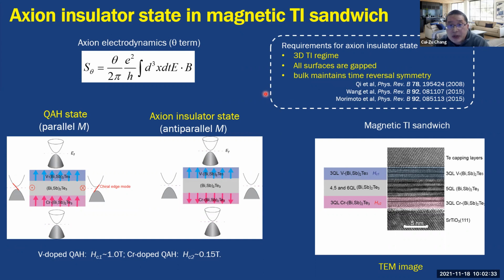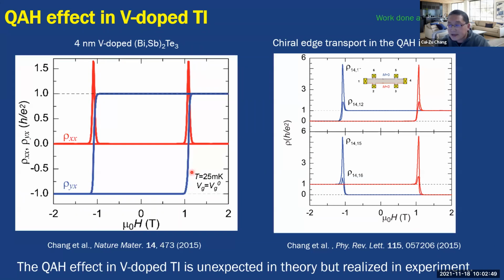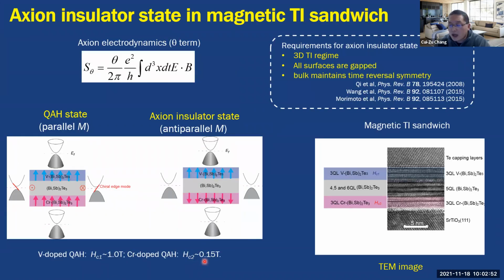So as I just introduced, we already realized the quantum anomalous Hall effect in chromium doped TI and also vanadium doped TI. And these 2 systems have different coercivity fields. In vanadium doped TI, the coercivity field is almost 1 Tesla, and in chromium doped TI the coercivity field is only 0.15 Tesla. So we were thinking to grow this kind of sandwich structure. The bottom layer is chromium doped TI, the middle layer is undoped TI, and the top layer is vanadium doped TI. At a very high magnetic field, they will align to the same direction.